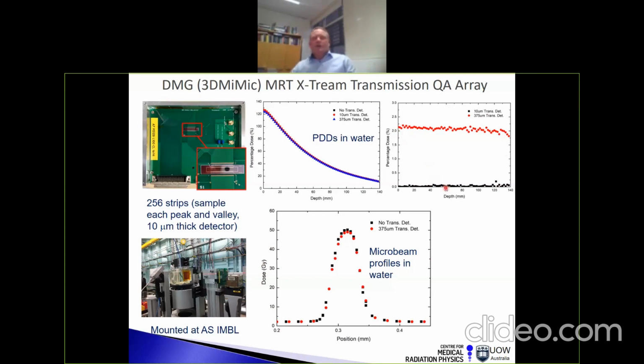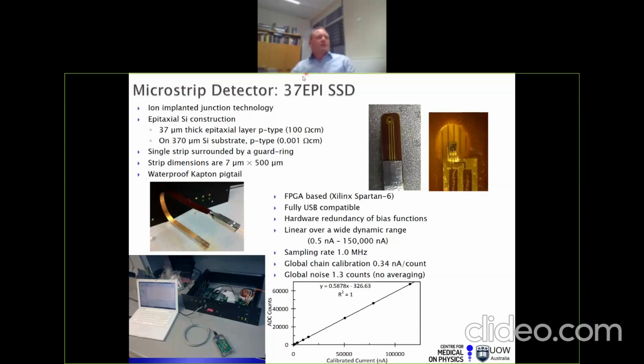Right, and then we also have some detectors here, silicon microstrip detectors, and this is so we can do the overall quality assurance. We want to do full dosimetry of our irradiation field, and this is a very, very challenging environment. Since we have very high dose rates and very steep dose gradients, we need a very large dynamic range. And so not only have we developed the detector, it's a waterproof detector, so we can put it inside a water tank, which is what they do in the hospitals, so it's standard quality assurance. Also the readout system and everything like that has been completely developed in-house, and the software.